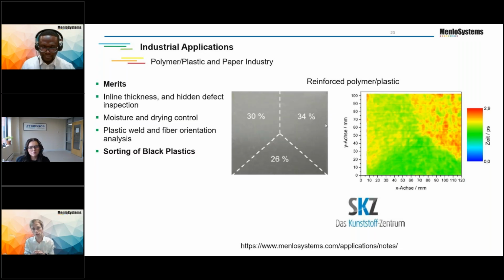That's a fairly difficult one actually to image. Because unlike optical microscopy where you might be looking at a two photon effect where you're only looking at focus, terahertz is interacting with the material as it focuses through the material and exits back out of the material. And because you're getting that interaction the whole way through the material, changing the z-axis through a material tends not to give great spatial resolution. Generally, terahertz performs best moving in 2 dimensions while staying at the focus of the beam. If you can orient your sample that way, it'll do very well. But beyond that, it can be a bit tricky to do that depth imaging in the z-axis.